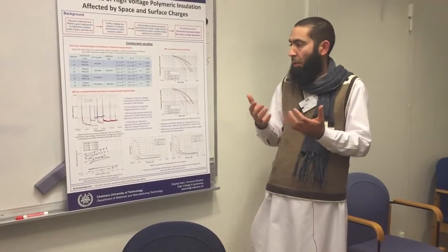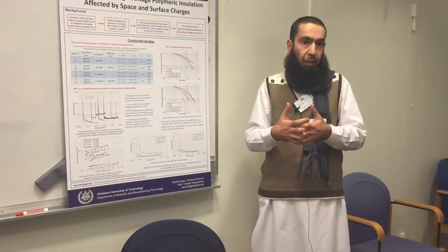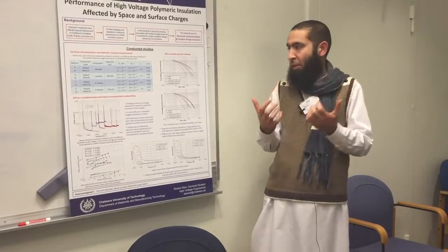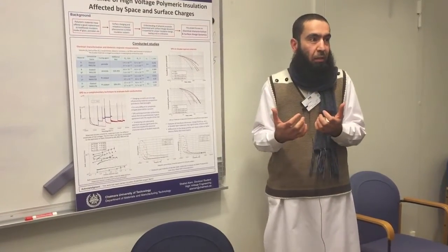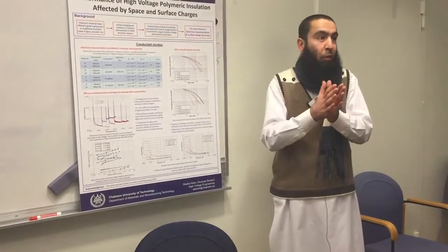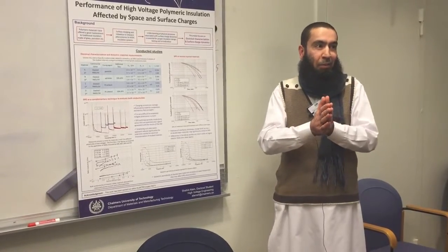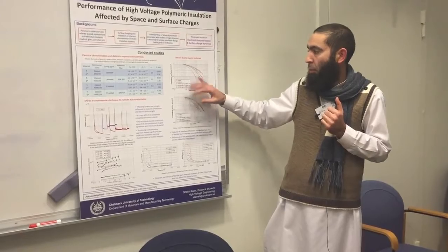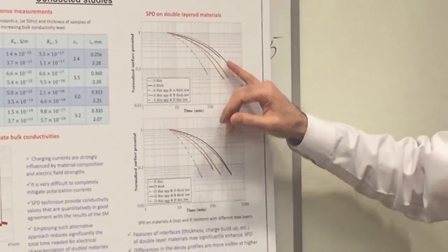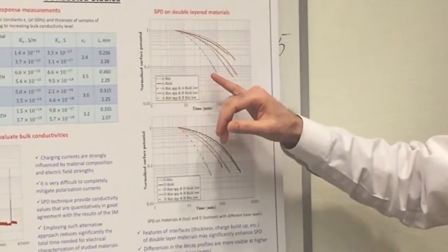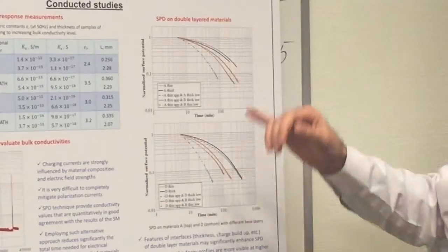Now also in high voltage insulations, basically materials simply exist in the form of layers, and then they interact with each other at the contact area, what we call the interface, and to try to investigate how they influence the surface charge dynamics, I tried to combine them, what we call a sandwich structure. And then one can see that when different materials are combined, the charge decay is significantly enhanced. So depending on the properties of the material, it can move in either direction.